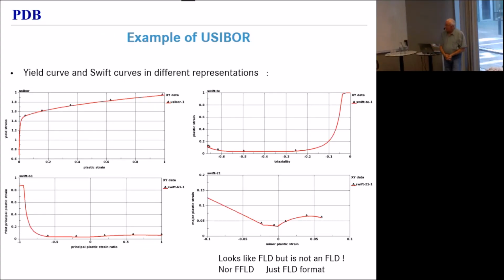Here you see what you can get with that. In the left upper corner, you see a yield curve. And right next to it, you see a plastic strain at start of instability in function of triaxiality, where my triaxiality here is positive in compression. So the negative values correspond to tensile states of stress. I did that on purpose. No, I didn't.